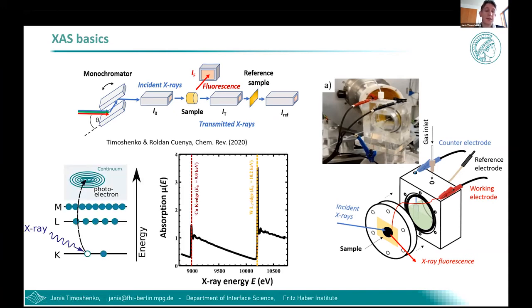So when we talk about X-ray absorption, what happens actually? Incident X-rays are exciting deep core electrons in our material from the deep core level states to some available higher energy states. And when the energy of X-ray photon matches the energy of these core level electrons, we see a significant rise in the absorption probability, which we denote as absorption edge. And then the fine structure above this edge is due to the transitions of these core electrons to localized or delocalized states. And in particular, in case of transitions to delocalized states, these excited photoelectrons can also interact with electrostatical potentials of neighboring atoms, and in that way, information not only about the electronic state of our atom, but also about arrangements of neighboring atoms is recorded in this fine structure of X-ray absorption spectra.